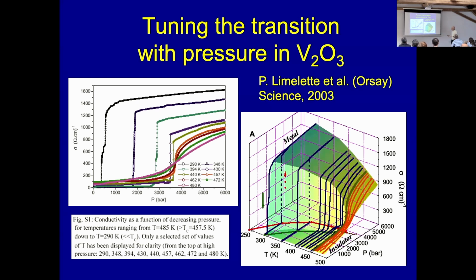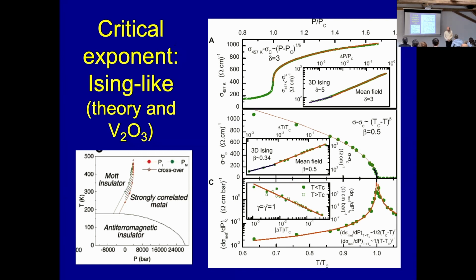And what we did at the time is we used the properties that we know for the Ising model to represent these different quantities. So this is just directly expressing the data. We were able to measure the critical exponents of the transition. The conductance minus critical conductance versus P minus Pc, where P is pressure, is basically a measure of the delta exponent associated with the response of the magnetization to an effective field. In the Ising analogy, we found that delta is close to 3, which is the mean field value. We even argued that if you get very close to the transition, you get back 3D Ising, which is delta equal 5. That was not so obvious from the data, but it's sort of there, and so on and so forth.